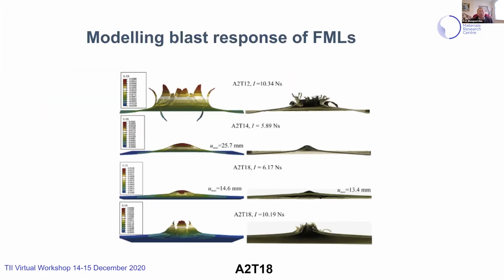Now is the modeling of blast response. On the left is from simulation, from modeling, and on the right from testing. So this kind of damage feature is being captured. We have very large deformation for aluminum, this rotation, and also these cracks, and the brittle splitting of fibers from the composite.